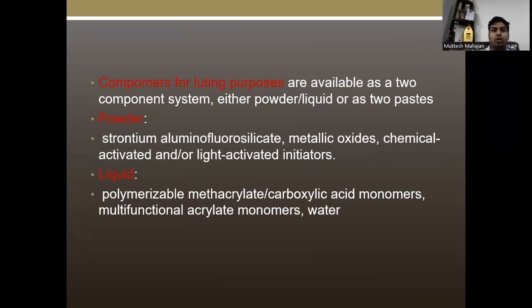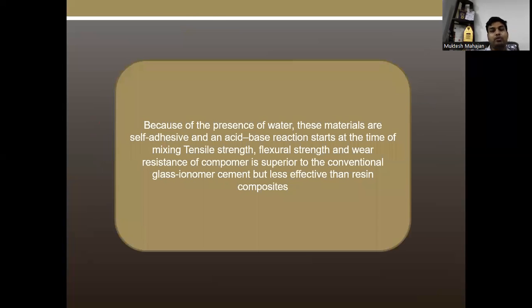The powder is made up of strontium aluminum fluorosilicate, metallic oxide, and chemically activated and light activated initiators. The liquid contains polymerizable methacrylate carboxylic acid monomers, multifunctional acrylic monomer, and water. Because of the presence of water, these materials are self-adhesive and an acid-base reaction starts at the time of mixing. The tensile strength, flexural strength, and wear resistance of the compomer are superior to the conventional glass ionomer, but less effective than the resin composites.